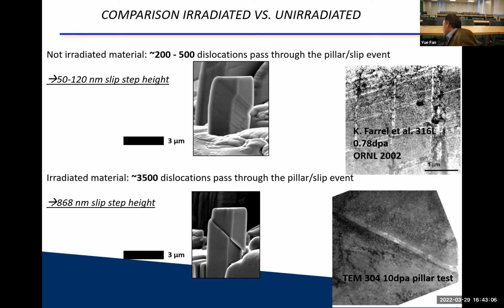Well, it's well known. This is the TEM of one of those deformed pillars. There's one of these channels where the deformation happened. Well, the radiation effects in this instance are maybe very small loops or stacking fault tetrahedrons. And when I have a dislocation passing through there, these defects get absorbed in the mobile dislocation, which means the next dislocation is going to have a little bit of an easier time passing through the same area. And so the 5th or 10th dislocation has very little radiation damage. That's why all the plasticity is localized in this channel. This is not particularly new, unfortunately.